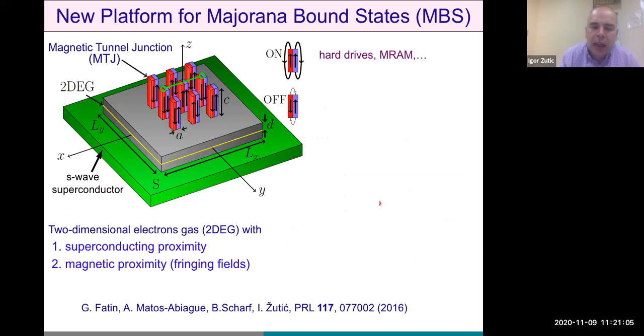This is now a standard S-wave superconductor. So just simple pairing of opposite spins. And next to it, we have a two-dimensional electron gas. So not a semiconductor nanowire, but a 2D platform. And above, we have arrays of magnetic elements. These magnetic elements can be spin valves or magnetic tunnel junctions, relatively well-known parts of our hard drives or magnetic random access memory, where we know that depending on the direction of magnetization, parallel or anti-parallel in two ferromagnets, there would be a different resulting fringing field. And these fringing fields could modify this semiconductor region underneath.